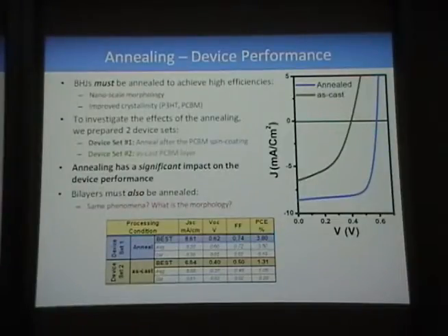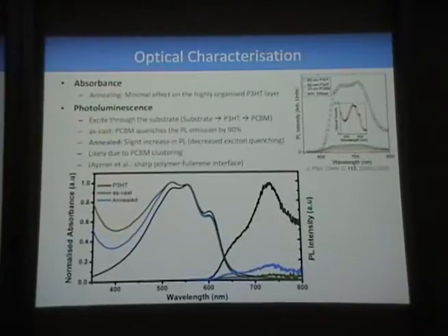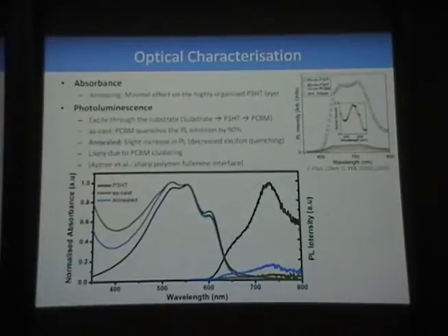But the question here is, is it the same phenomenon, and also, what is the device morphology? So first, we turn to optical characterization to get an idea of what's happening in the film. From the absorption spectra, shown here, these are the normalized absorptions. Annealing has a minimal effect on the highly ordered P3HT layer. So that's what the absorption spectra is telling us. From the PL, we looked at exciton quenching, and in this case we excited through the substrate. In the as-cast structure, which is the green trace here, you can see that the PCBM quenches the PL by up to 90%. And in the annealed, you get a slight increase in the PL, and this is due to the decreased exciton quenching.